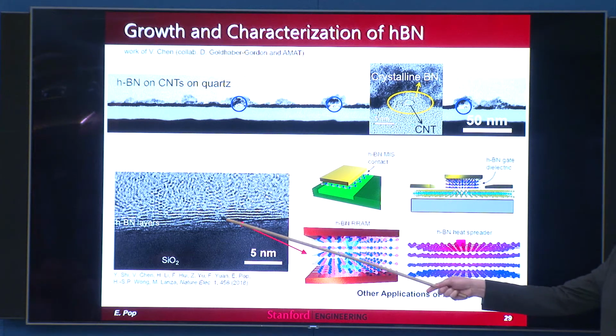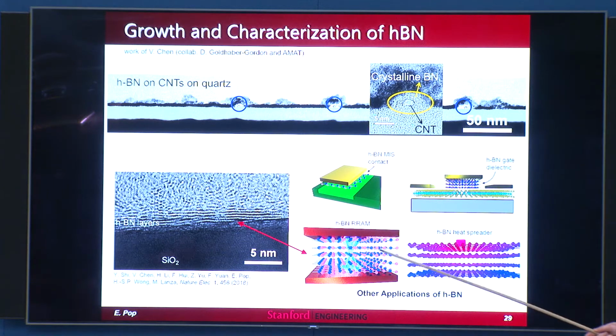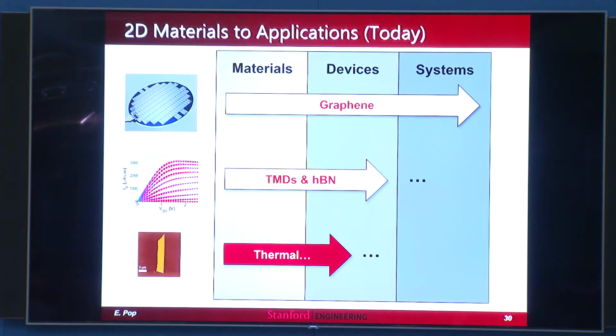We can also grow multi-layer boron nitride. For memory applications, it turns out these are defective, so they make decent resistive memory. But we're also interested in boron nitride heat spreaders, as you can imagine, because the thermal conductivity is supposed to be pretty good. So we're in the process of measuring their thermal spreading properties at the moment, since we do quite a few thermal measurements.